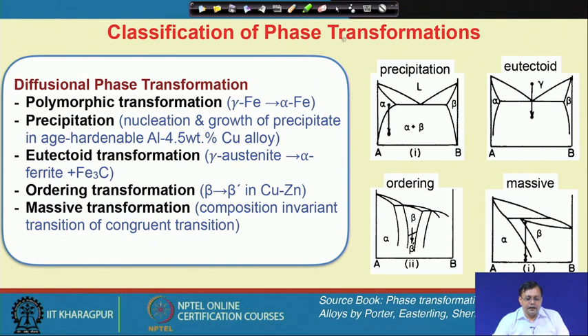Now, let us come to a diffusional phase transformation. A diffusional phase transformation implies that long range atomic diffusion is required to initiate this phase transformation and to complete the phase transformation. Okay. One is the initiation, which is somewhat like nucleation, and also the growth. So, mostly there are so far 5 different types of diffusional phase transformation that have been observed. So, these 5 types are polymorphic transformation.